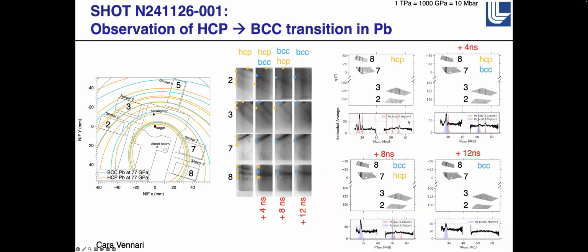This shows an observation. We ramp compressed lead, and we saw the HCP to BCC transition in lead as it was being compressed. And so here Kara has labeled the orange diffraction peaks as the HCP peaks, and the blue ones are BCC. So at time equals 0, we go from a complete HCP structure to 12 nanoseconds later, we can see a complete BCC structure, and we can see the transition between it. And we're now upgrading this to a new diagnostic, which we're going to get all eight detectors on it, and we're optimistic that we've cut the background down substantially, that we'll be able to get much better data in a year or so.